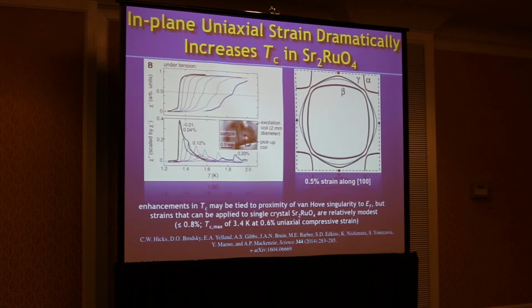But it is something that you can play around with in other ways of strain. So here's work that's used uniaxial strain to try to tweak the band structure of strontium ruthenate. And in this work from Andy Mackenzie's group, they've doubled the transition temperature by applying uniaxial strain. And what they think is going on here is that this band is getting closer to the van Hove singularity over here, as they apply this uniaxial strain. Strontium ruthenate's a brittle material, so the highest that they could get was 0.8% strain before they broke their crystals. Nonetheless, they did increase the transition temperature significantly, which is great.